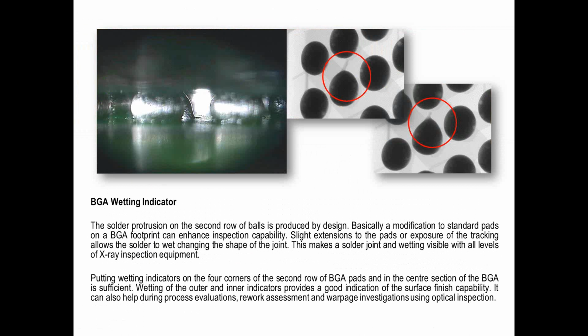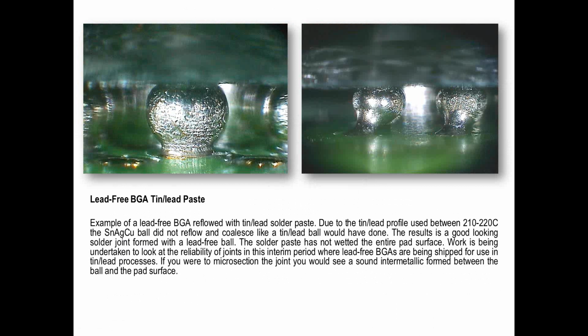And this gives you an indication that perhaps the wettability, solderability of the board is better. But again, the idea of this is to aid inspection to make it easier, particularly on a low-tech or low-cost X-ray system. Now, hopefully, most companies don't have mixed processes with tin lead balls or lead-free balls and a tin lead process. But these are typical examples of what we saw during the transition to lead-free technology.